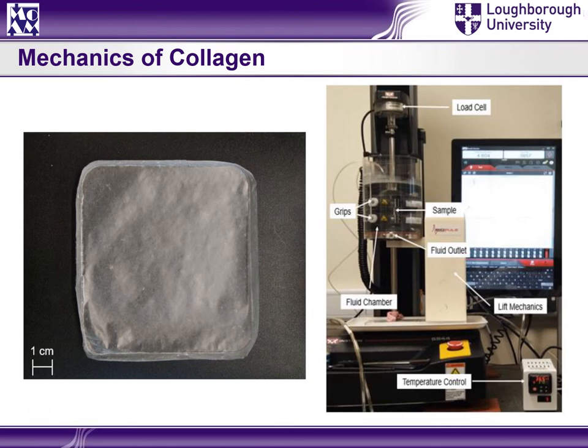Another material which is very important and prominent in our body is collagen. It forms one third of all the proteins in our body. We have produced 100% collagen films in order to study its properties rather than use live tissues, which would be a mixture of different constituents. Here we also considered the difference of the environment. We performed the tests on dry specimens, hydrated materials, and fully immersed material in a water bath at different temperatures.